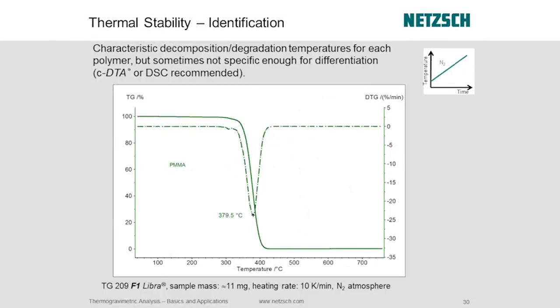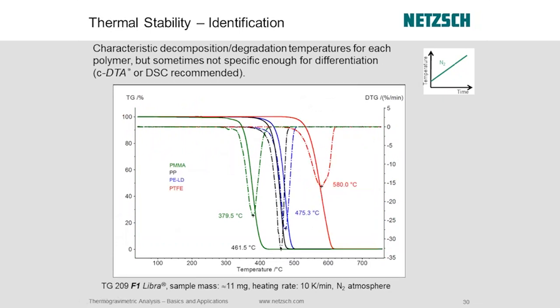Okay, thermal stability identification. We can look at the thermal stability in nitrogen of different polymers. I'll go through this a little bit faster. There are four polymers here: PMMA, polymethyl methacrylate, polypropylene, low density polyethylene, and PTFE. We run them in nitrogen, and we see they've got a characteristic degradation temperature, and you can very easily separate these. You could say, if my degradation's here, it's probably PTFE. If my degradation is here, it's probably PMMA, and so on.